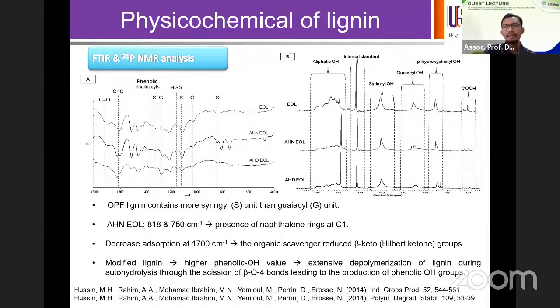And we also use phosphorus NMR in order to quantify the aromatic content. What we observed was that when we modify the structure of lignin via combinative pretreatment, there will be more aromatic rings, or aromaticity, present in the lignin structure. And due to this, it gives us more properties later on, for antioxidant activity or solubility. We also noticed that after we introduced the organic scavenger, the carbonyl ketone peak, especially at 1700, is slightly reduced. So it means that there is some interaction, because the carbonyl functionalities are very active in interacting with the organic scavengers.